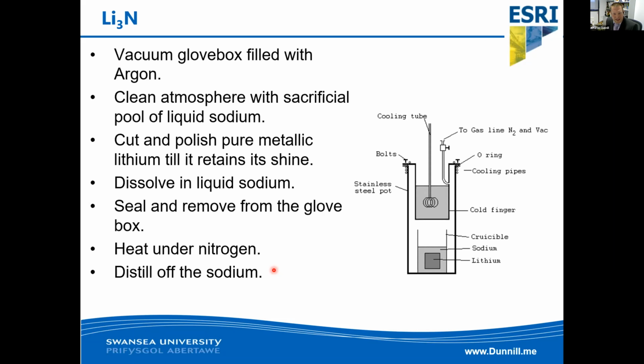So you imagine this, you're in this glove box, your arms are stuck, it's about 50 degrees centigrade, your sweat pouring down your face, trying to do this whilst you're polishing pure metallic lithium until it shines inside the glove box and then putting it into this reactor vessel. So you put the lithium into more liquid sodium, seal the whole thing up, and then heat this out of a glove box for a good number of hours, if not a few days, under a nitrogen atmosphere.